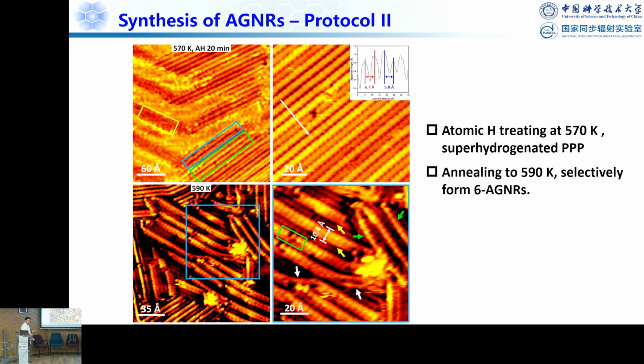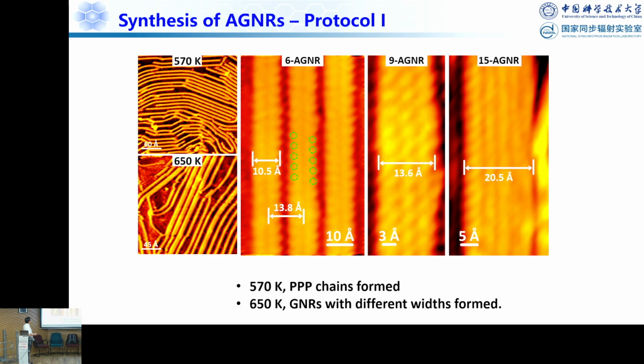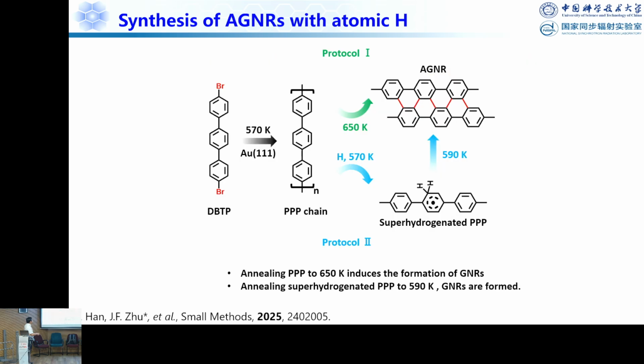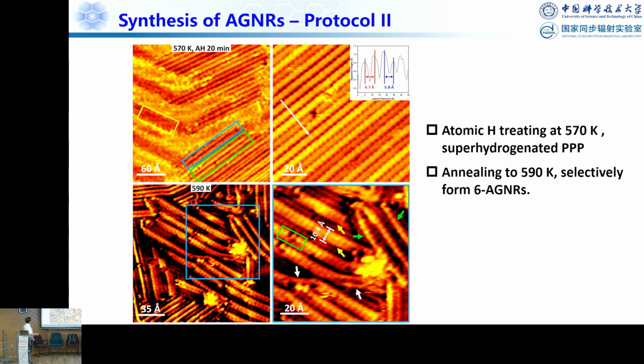So we think, first, these super-hydrogenated PPP chains, as we draw here, can both form graphene nanoribbons. And also the other thing is the temperature is lower. Now it's only 590 Kelvin, whereas you can see the other graphene nanoribbons form at 650. So at this low temperature, there's no further fusion of the chains into wider graphene. That's why we think it forms relatively uniform width graphene nanoribbons.